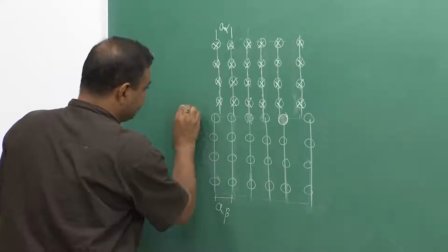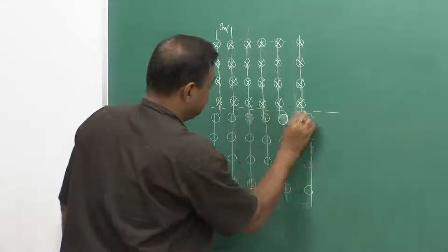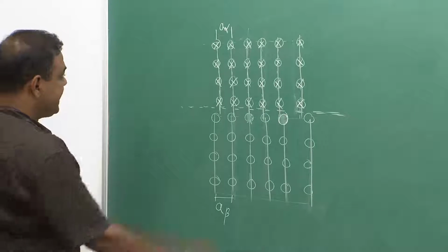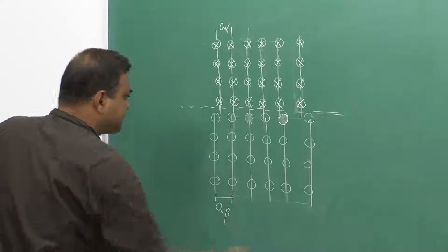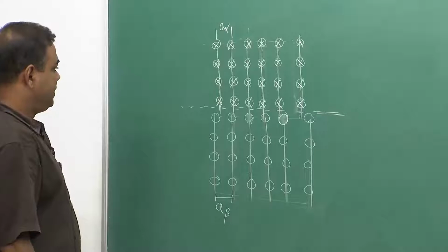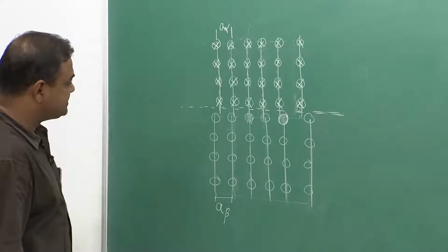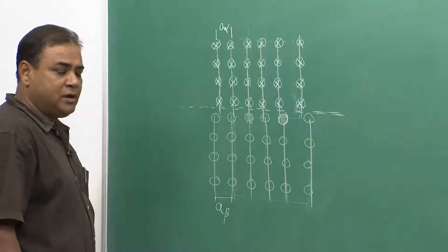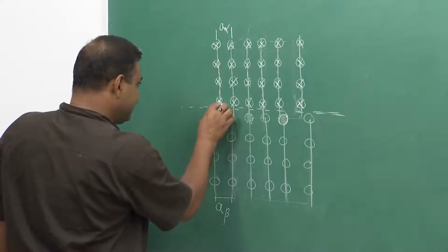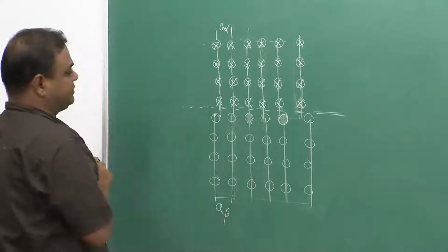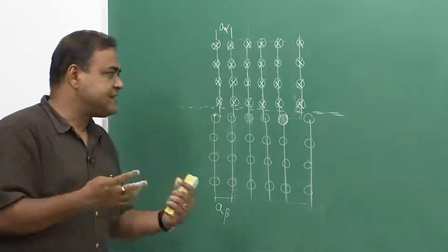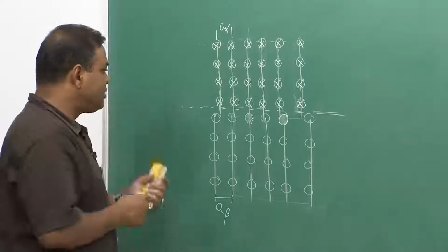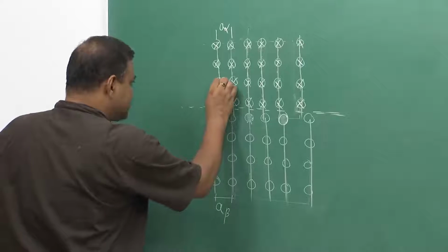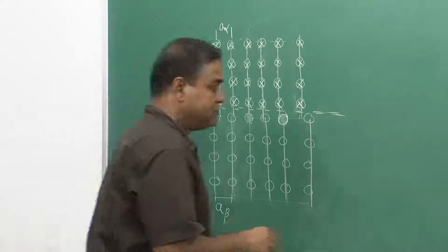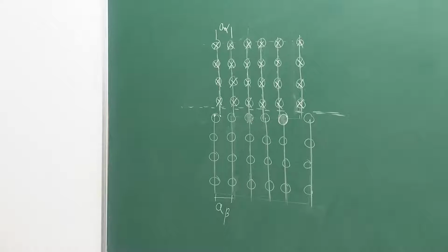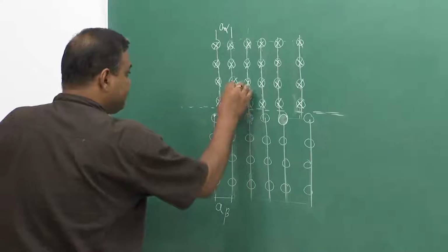I see there is an interface along this line, but at the same time I see that there is one lattice plane which is perfectly matching, it is perfectly going through. Now, there are other lattice planes which are not exactly matching. For example, if you see this, there is a little deviation, from here to there. But the system would always like to have a match. So, in order to match this, these lattices will be distorted like this. If I try to draw in red color, you will see that these lattices will be a little distorted.